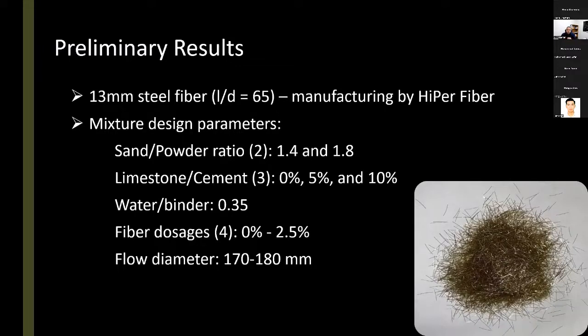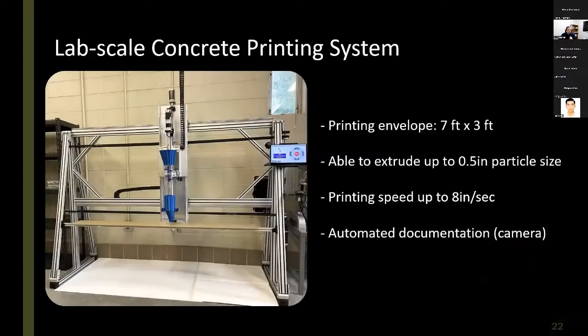And then again, based on some initial testing, we learned that the workability range of 170 to 180 millimeter of flow with the flow table is basically the range that we need for our mixtures. So that's what we use for all of our mixtures. And that means that they had the same level of workability, and we had to add higher dosages of superplasticizer to mixtures with more fiber to reach that target workability range.